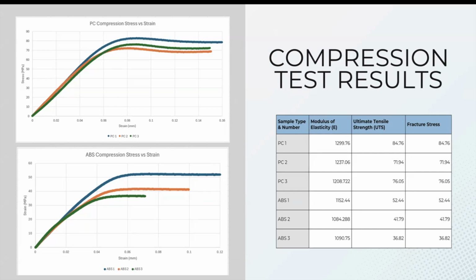Moving to the ABS results, overall stresses were noticeably lower compared to PC. The ABS curves reached maximum stresses between roughly 36 and 52 MPa. And ABS1 had the highest strength at 52.4 MPa, while ABS3 showed the lowest at 36.82. The modulus values for ABS range from about 1,084 to 1,152 MPa, confirming that ABS is less stiff and less resistant to deformation.